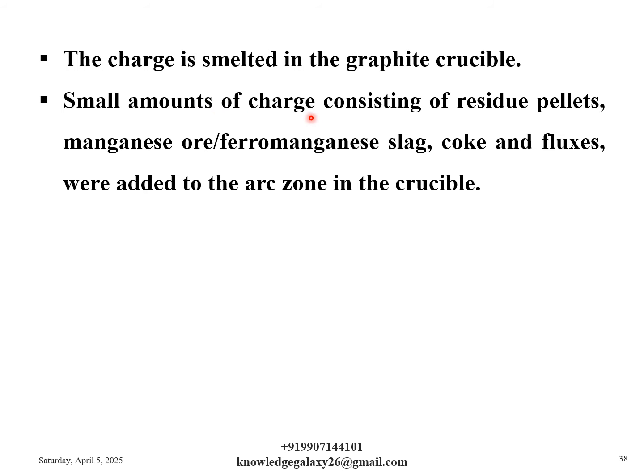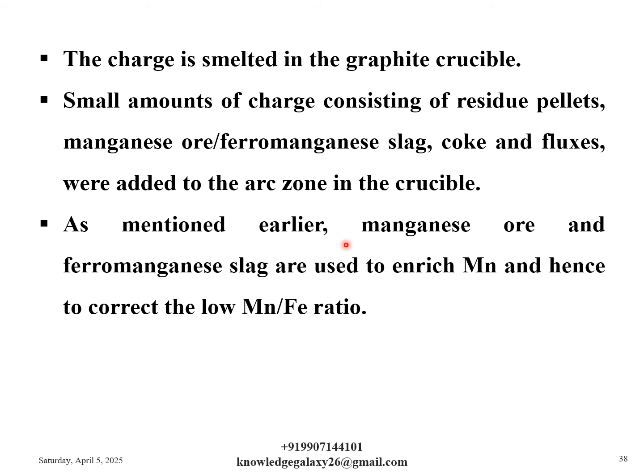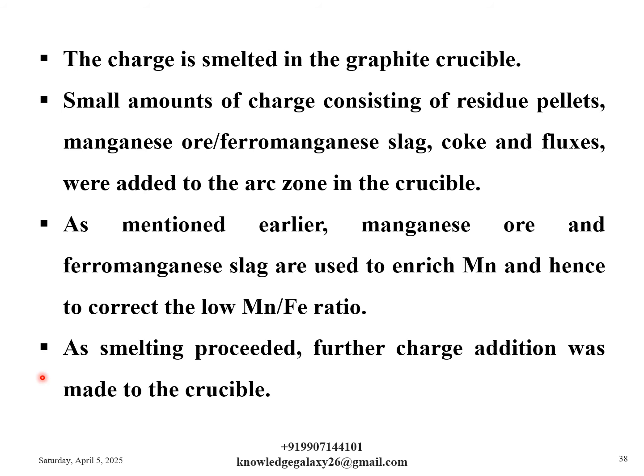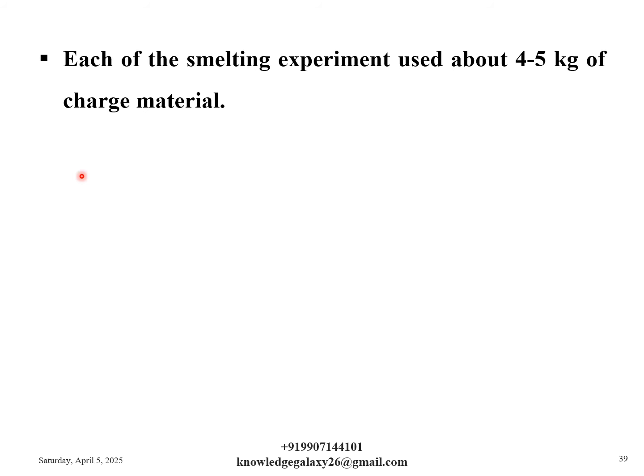Small amounts of charge consisting of residue pellets, manganese ore and/or ferromanganese slag, coke and fluxes were added to the arc zone in the crucible. As mentioned earlier, manganese ore and ferromanganese slag are used to enrich manganese and hence to correct the low Mn by Fe ratio. As smelting proceeded, further charge addition was made to the crucible. Each smelting experiment used about 4 to 5 kg of charged material.